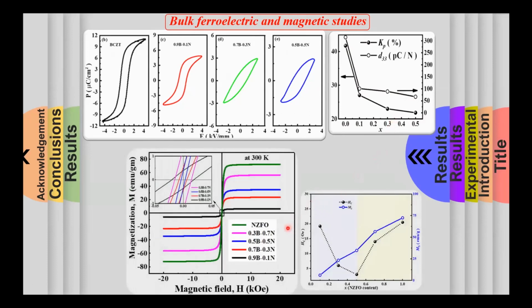Here we see the magnetic behavior, and the following observations were made. The composites exhibit extremely slim, well-saturated ferromagnetic hysteresis loops, indicating the presence of an ordered magnetic structure in the composites. And the saturation magnetization was found to increase systematically with increasing ferrite content. Here we see the magnified view. The composites showed very small coercivity values, in the range 5 to 20 Oersted, and this reveals their soft magnetic nature.